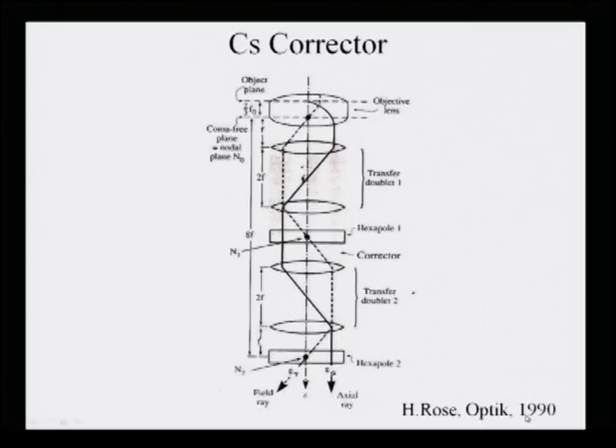That is what is shown in the slide. As you can see, this is the standard objective lens, and the electron beam from there passes through a set of spherical lenses and hexapole lenses. And when it passes through all this, the hexapole lens does not affect the paraxial path of the rays, but it corrects the aberration. In fact, it has been reported that it is possible to actually have a negative spherical aberration constant, and by getting that, one can actually break the resolution barrier of 1 angstrom.